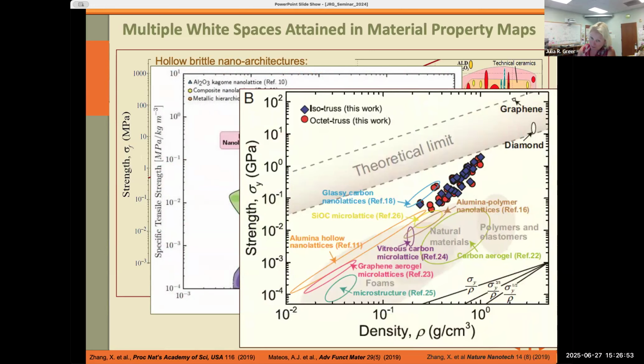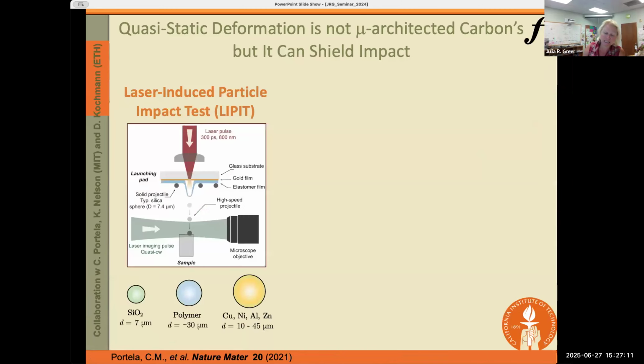We learned that carbon, the very brittle carbon that still didn't recover, turns out that it has additional benefits. For example, it's the only material that gets close to the theoretical limit at the higher density regime. And so this is a very interesting finding. And in fact, I want to spend a little bit of time validating carbon. So it turns out that we just weren't doing the right experiment. Like I said here, quasi-static deformation is not microarchitected carbon's forte.